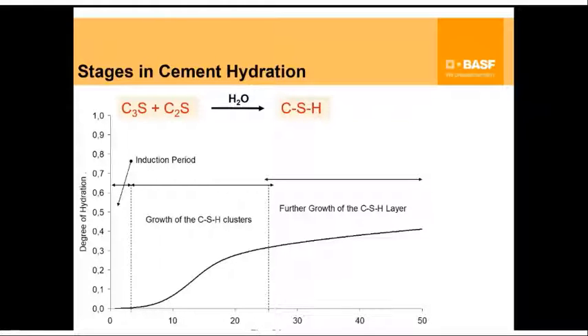And what happens is there is this period of time, which is a quiet or the sleeping period, which is the phase when a lot of the initial nuclei or very small particles of CSH are being formed. And this is the key step which then allows the next phase, which is the growth of the CSH cluster.